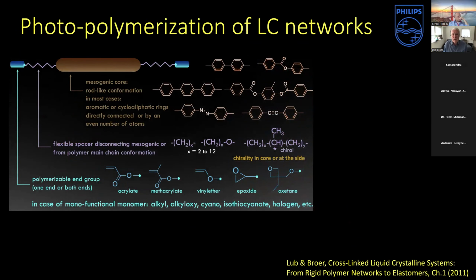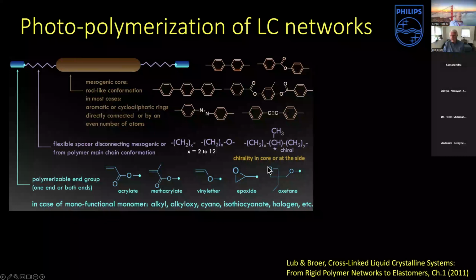And meanwhile, we at Philips, but also at Merck at that time, developed a whole range of liquid crystalline materials, all with this kind of more or less general chemical composition. So normally they consist of an aromatic core. They have a flexible spacer. You need some flexibility here to decouple the polymerization from the order of the mesogenic unit. Normally alkyl spacers, but you can also have ethers. And then we have the polymerizable end group. In most cases, we are using acrylates or methacrylates, but it can also be vinyl ethers, epoxides, or oxetanes, and we basically have synthesized them all.